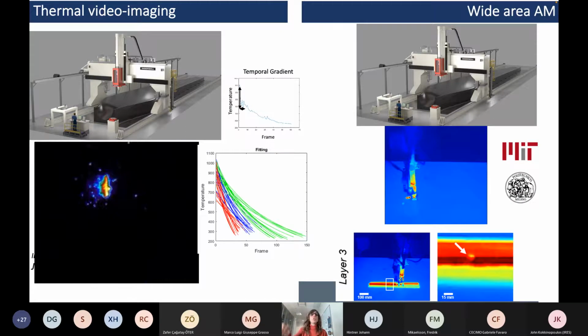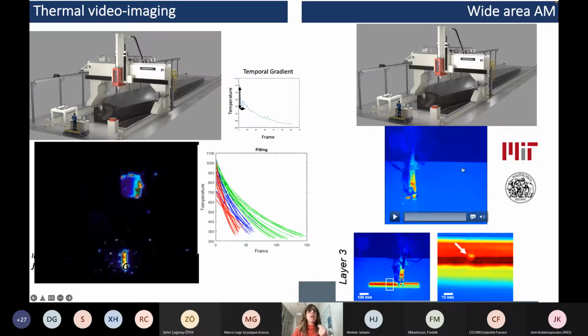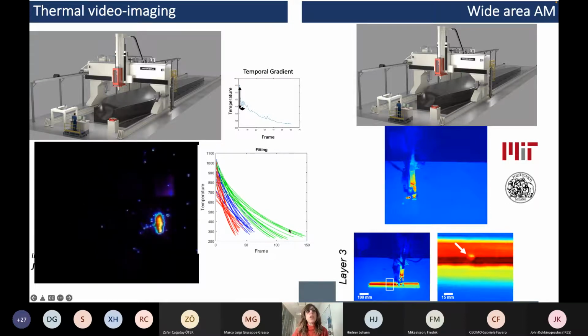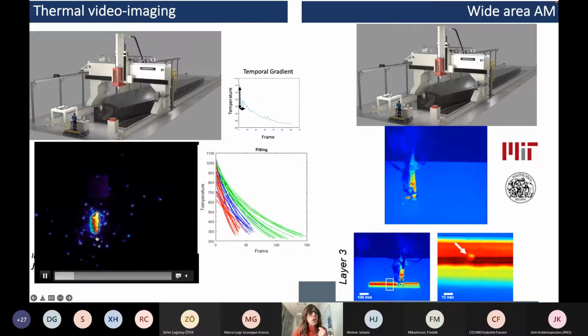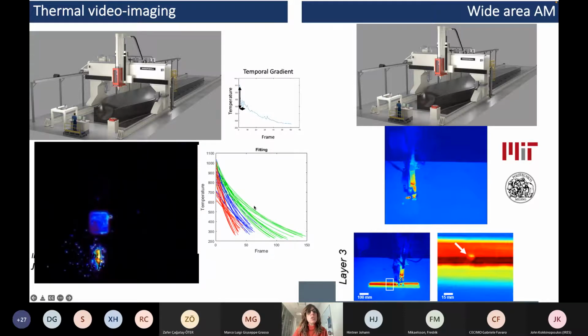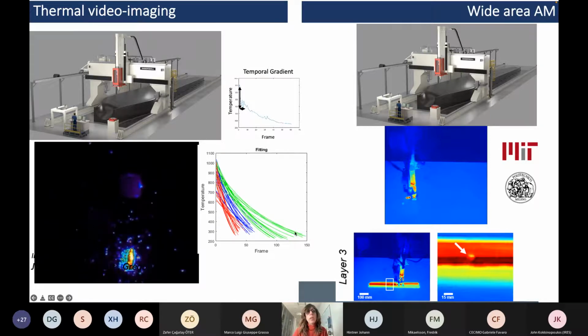I think I'm moving to, let's say, close to the last examples, just to show that you can not just play with video, but also with thermal video. And in this case, you can have some sort of history of what is happening in terms of the thermal cooling, which is observed at each specific location, thanks to this thermal imaging that in this case is done on metal powder bed fusion. At each location, you can follow the cooling history and maybe derive or see that in some location, the cooling history is too fast or too slow. And so this is going to create problems in terms of what you want to do at the end.